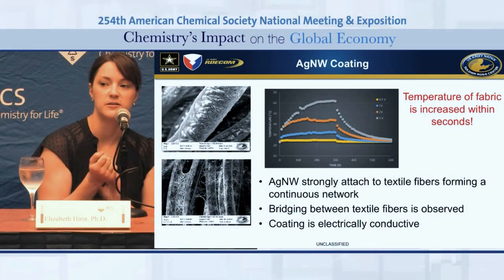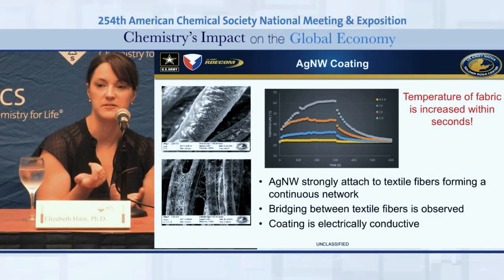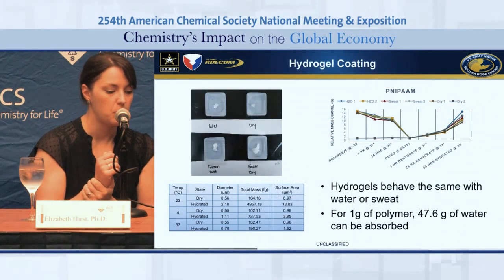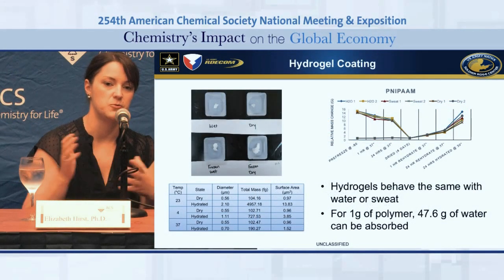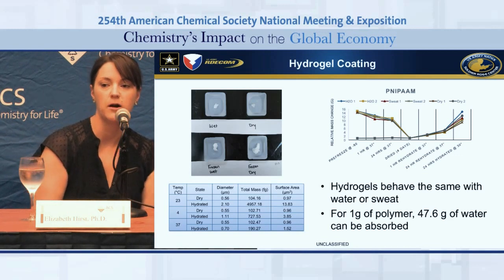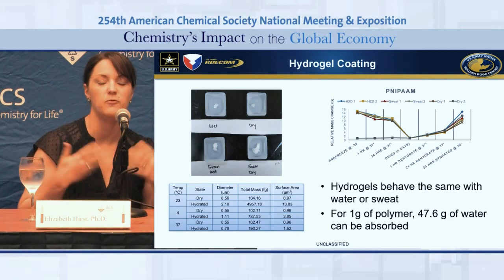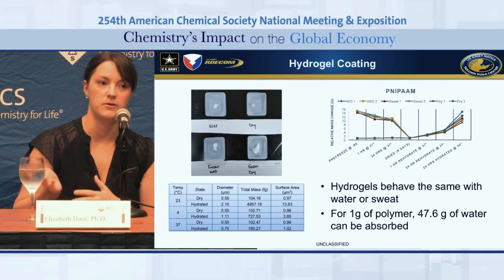So the hydrogel coating will address moisture management for the soldiers. So one of the problems is that their base layers, while polyester, are very good at wicking water away from the skin. If you're in extreme cold, the rate of evaporation out of the fabric to the air is very slow, and consequently it's freezing. So frequently where their pulse points are, they're experiencing icing of the garments, which is obviously very uncomfortable. So we're hoping to apply a hydrogel, which absorbs numerous times its weight in water, to these problem areas to help move water away from the skin and out of the garment.